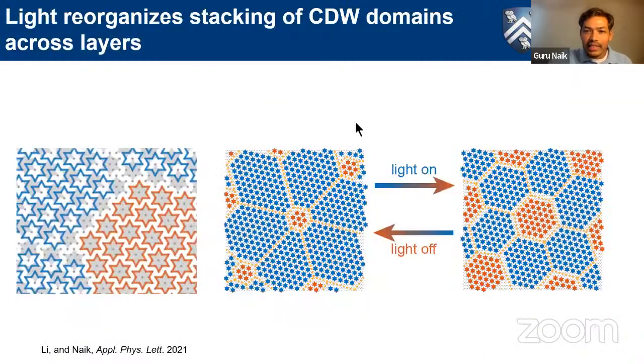Okay, so we hypothesized that at room temperature, probably there exist two different stacking configurations. Here, the bottom layer domains are all shown in gray, and the top layer domains are all shown in color. And we have two different stackings here. One is blue stacking, which is staggered, and the red one is center-to-center stacking on top of each other. So we said at room temperature, both these stacking domains coexist, and just that the ground state one, which is the blue stacking, is more preferred and has bigger domains. When we turn light on, somehow the blue domains shrink, letting the red domains grow. And that's what changes the optical properties. So this was our hypothesis.